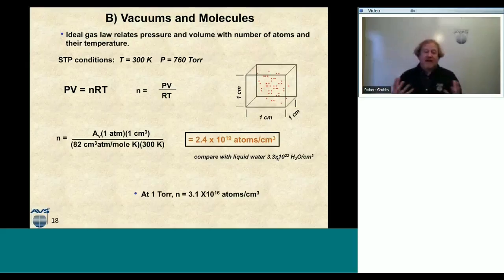Now, that's not to say that number is always the same, because at 1 torr or maybe 5 torr or 3 torr, that's the typical pressure that ALD reactors are run, we get a value of about 10^16 atoms per cubic centimeter in our little box. So it's obviously proportional to pressure. So the higher the pressure, the more atoms we have in our cubic centimeter.